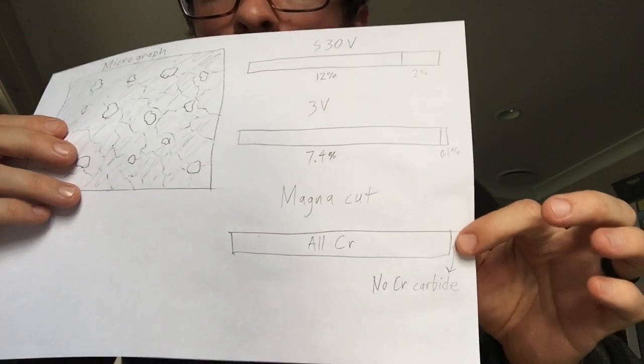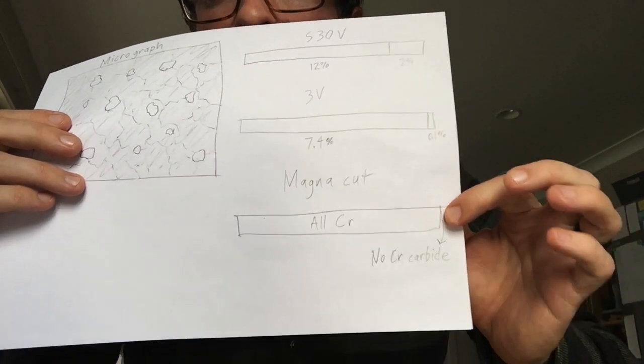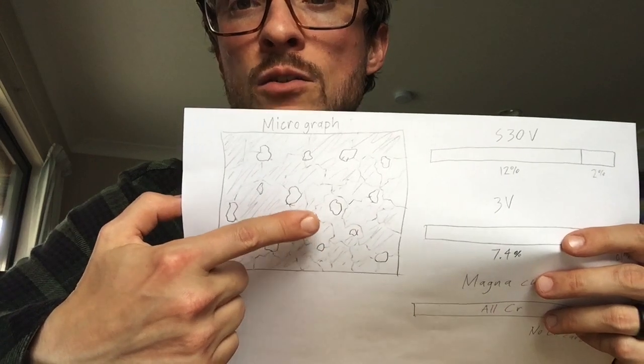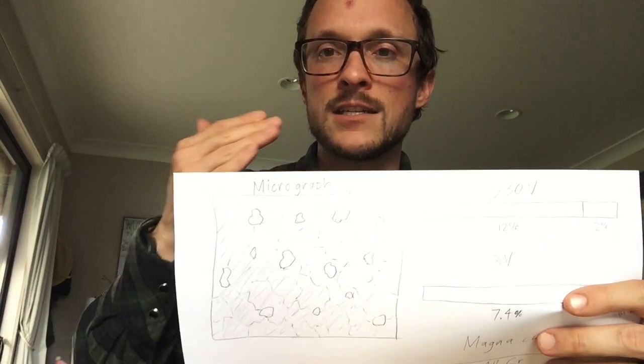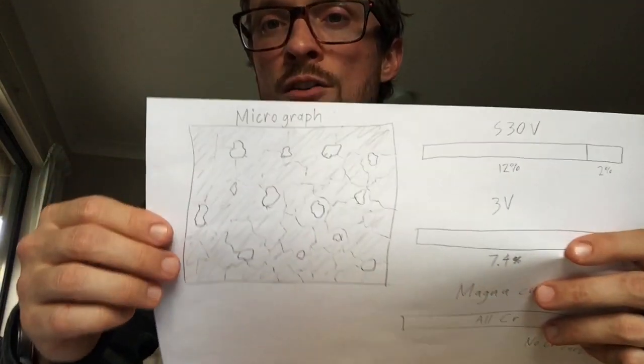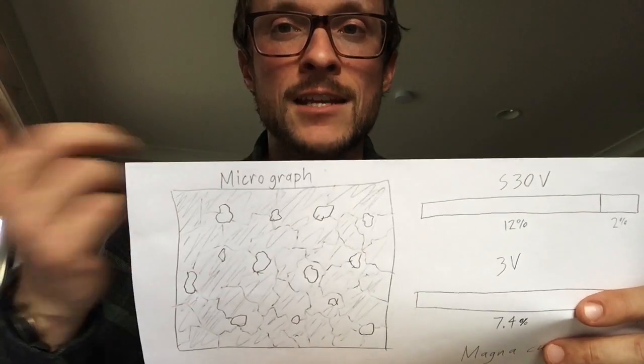So Larrin asked this very important question: what if there was absolutely no spillover into carbides with your chrome? What if every bit of chromium that you put into the steel, every last bit, went into the steel matrix? So you had a steel which had the optimal toughness for that level of chrome, which also didn't have something competing with the vanadium carbides. The chrome actually competes with vanadium carbides and pulls carbon away from them and makes them less useful. And it forms carbides which are much softer and don't add to wear resistance as much. So this is the question.